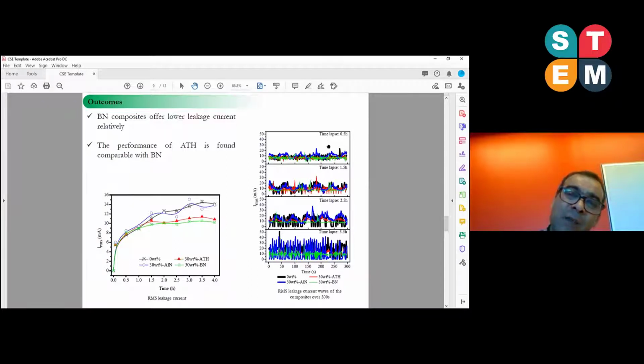At the start of the experiment, the leakage current is quite low in all four samples: pure, ALN, ATH, and BN as well. Then it increases linearly. We can see that in the last hour of the experiment, the increment in the leakage current is quite high. The high current is seen in the pure silicone rubber insulation and in the ALN sample. Here the green line shows the leakage current in the BN sample, and in the BN, the leakage current is relatively much lower compared with its counterparts.